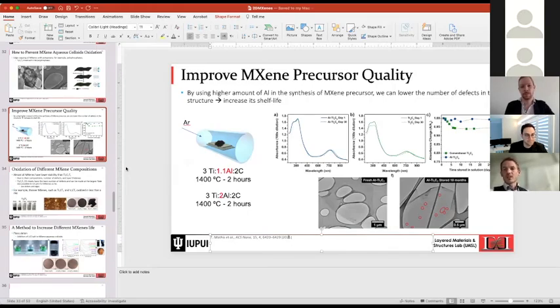So the next one is, why are nitride MXenes not as widely used as carbide MXenes? So that goes to how we can synthesize MXenes. The nitride MXenes are in general less stable. And that, in simple terms, is because of the extra electron of nitrogen versus carbon. When we want to synthesize these nitrides, usually everything dissolves together instead of having the selective etching, because the bonds are not as strong as in the carbides. So that's the simple explanation. It's not that we are not interested in nitrides, but that the synthesis has been very challenging.